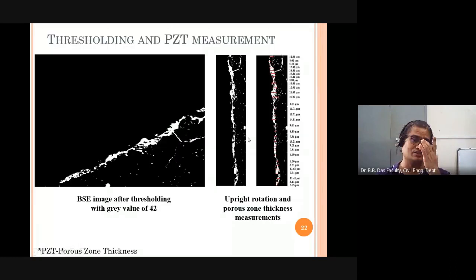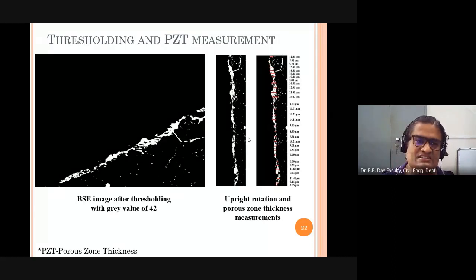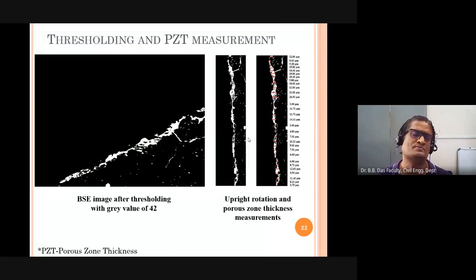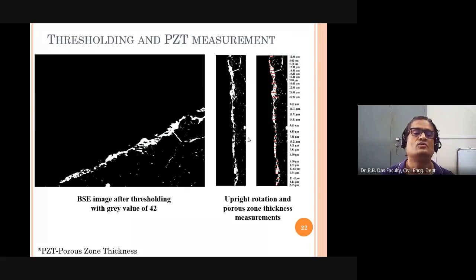Exactly. What we did was some image analysis programming, and through the programming we did BSE, that is backscattered electron, image thresholding. We realized that with a gray value of 42 and below, because the highest for the pore was 82, so around 40, we can say that below 42 is my pores, and more than 42 is my other materials, maybe steel, maybe concrete, maybe the aggregates or other materials or hydration products.